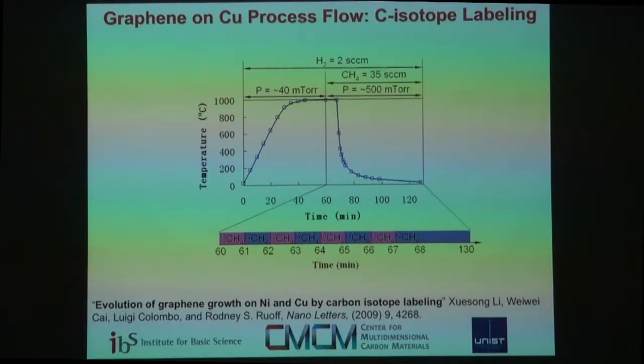So we thought if we had a 25 micron thick commercial foil or Alfa Aesar foil, maybe we'd get few layer graphene if it was a consequence of the carbon atoms dissolving down into the copper, and then when we cooled the copper, precipitating to the surface because the solubility at room temperature is really zero and you have a thin foil, so they don't have that far to diffuse. But irrespective of the thickness of the copper foil, we always got essentially monolayer. So we chose 25 micron thick and we got monolayer. It was surprising. So we tried 100, 200, monolayer. And so we felt pretty sure that it was a consequence of surface-mediated growth at 1040 degrees C and not a consequence of the cooling step.